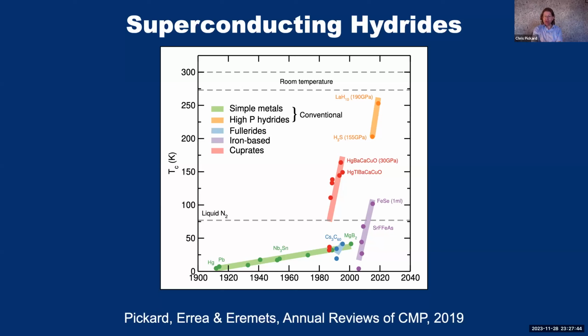Now, in both the cases of hydrogen sulfide and lanthanum hydride, there had been theoretical predictions that these would be good materials to look at, and indeed the experimentalists involved were very much driven by those theoretical suggestions. Right from the very beginning there was a clear synthesis between experiment and theory. Now, of course, this is very tempting. We've got a line that's rising very steeply with time, and it tempts us to think that there may be the possibility of finding room temperature superconductors, and there's a wide effort across the globe of people using structure prediction techniques and prediction of superconducting transition temperatures to try and see whether we can reach this limit.